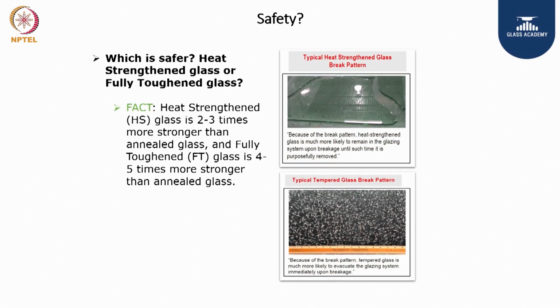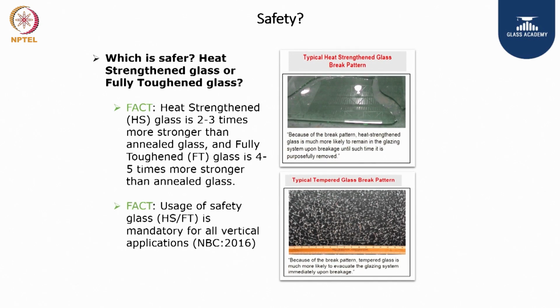Now the fact is that heat strengthened glass is 2 to 3 times stronger than normal annealed glass, the float glass, and fully toughened glass is about 4 to 5 times stronger than annealed glass. So if we are designing for resistance against impact, the ideal choice would be fully toughened glass. Having said that, the usage of heat strengthened glass or fully toughened glass, which is labeled as safety glass, is mandatory for all vertical applications of glass, as per the National Building Code, the latest revision 2016.